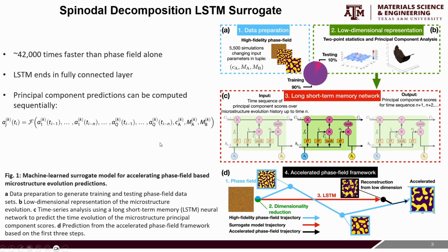One thing to notice about our architecture is we start with the phase field model, and with these three inputs, we are able to generate the microstructures. We can take those microstructures and essentially do a Fourier transform using 2-point statistics, finding the distribution of the phases. Basically telling you how likely it is to find a certain phase at a certain location.